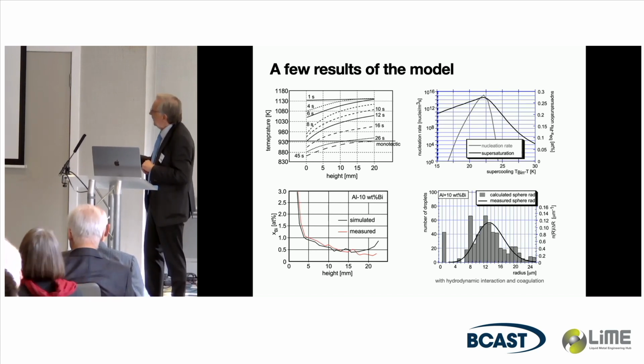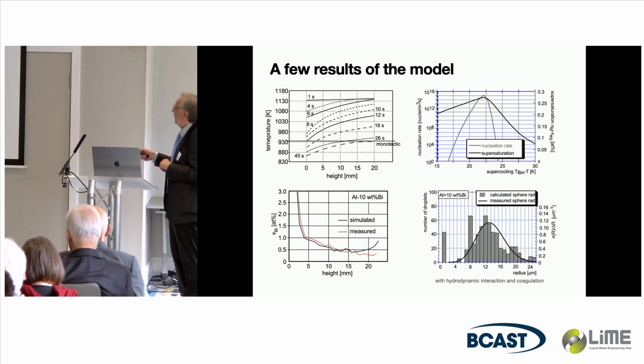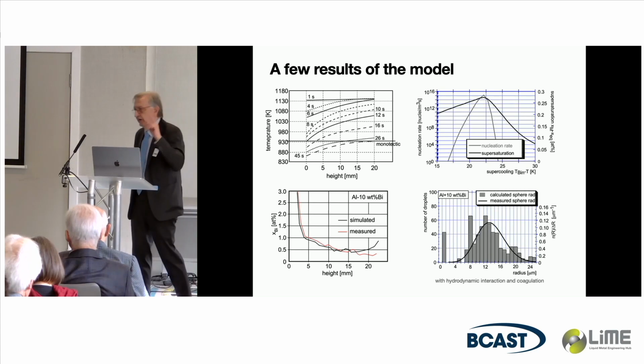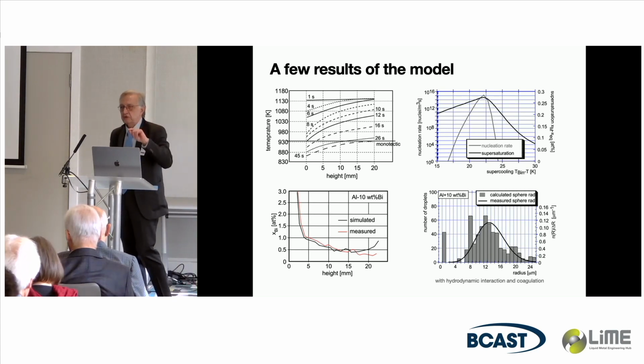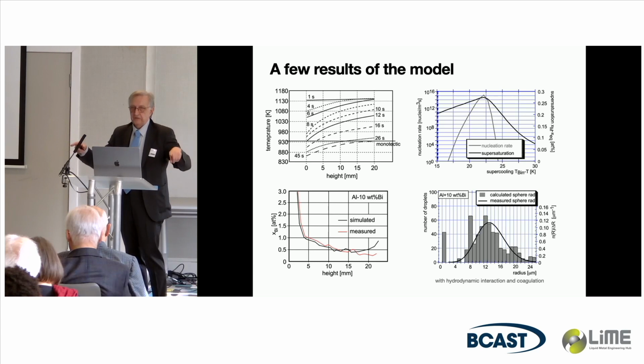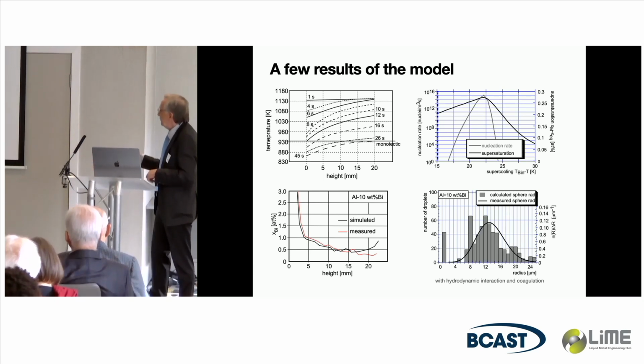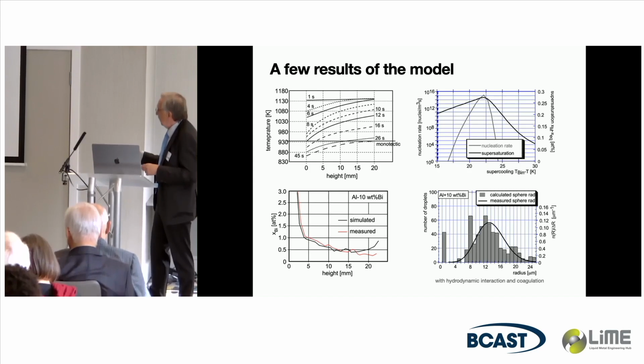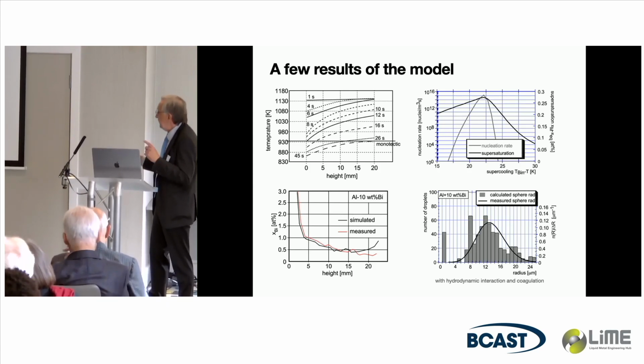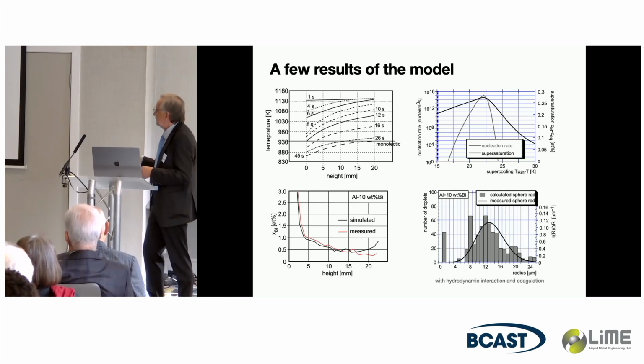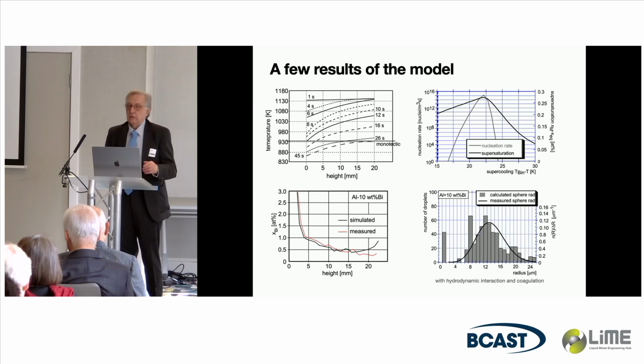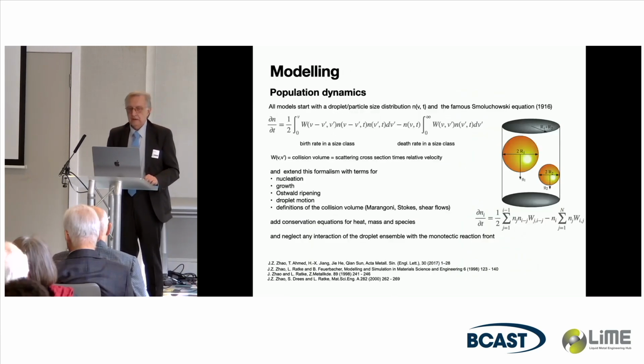But nevertheless, we were lucky that the measured bismuth concentration and the simulated one agree very well, and for the droplets stemming from the phase separation, not from the monotectic reaction, you have to deconvolute the particle size distribution. If you deconvolute it and say these are only what is left over from the phase separation in the miscibility gap, the calculated sphere radii and the measured sphere radii agree very well. So, sounds good. I think it's not good enough.